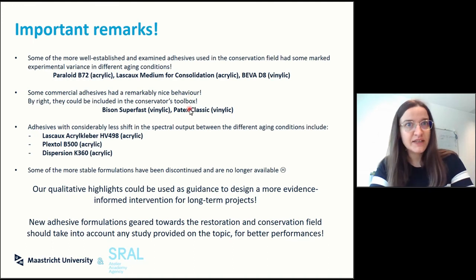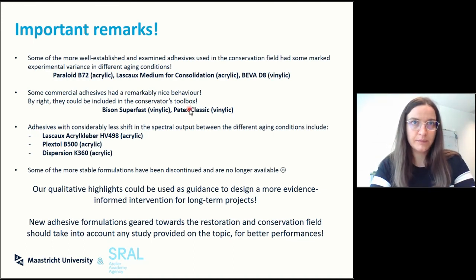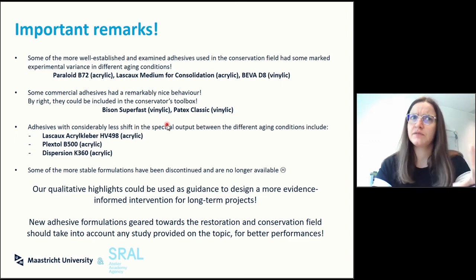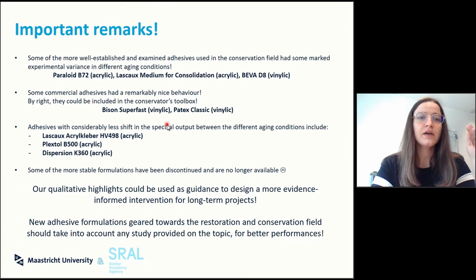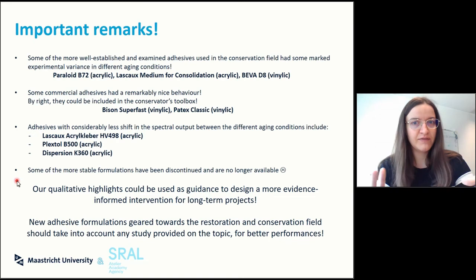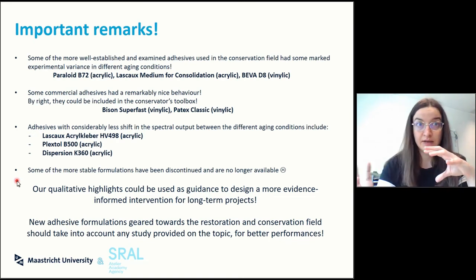Some of the commercial adhesives that several conservators tend to avoid could by right be introduced in the palettes because they show a remarkably consistent behavior, both macroscopically and from the chemical FTIR. Some adhesives deserve praise for having a consistent and remarkably contained shift regardless of the aging. So these adhesives can be considered very aging resistant.